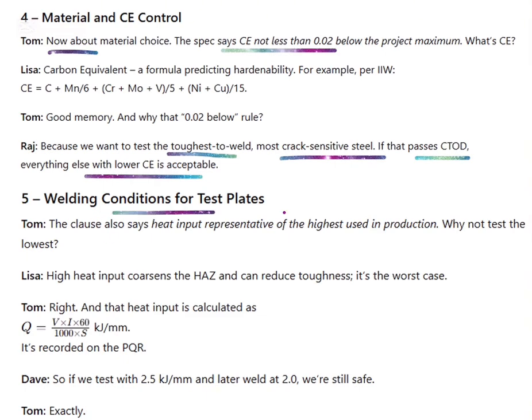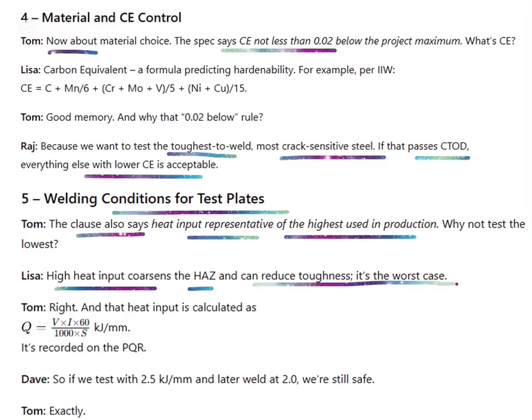The welding conditions for test plates. The clause also says heat input representative of the highest used in production. Why not test the lowest? High heat input coarsens the heat affected zone and can reduce toughness. It's the worst case, right? And the heat input is calculated as regards the PQR. So if we test it at 2.5 kilojoules per mm and later weld at 2.0, we are still safe. Exactly.